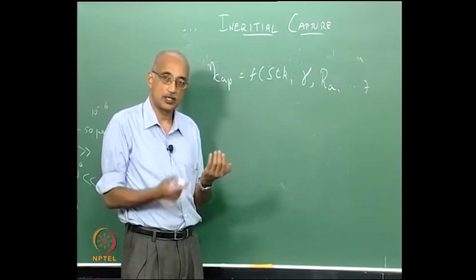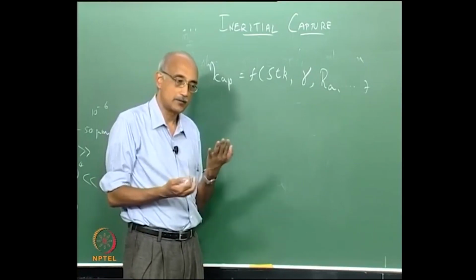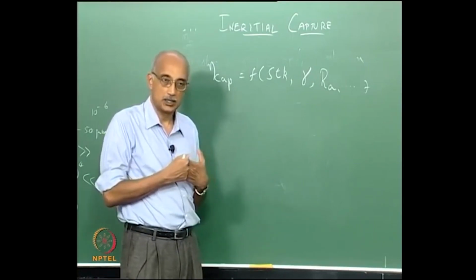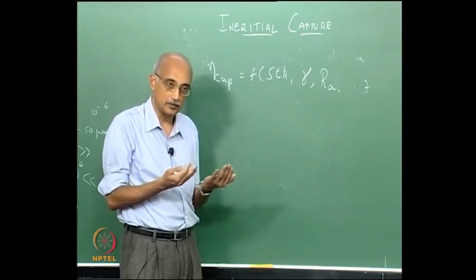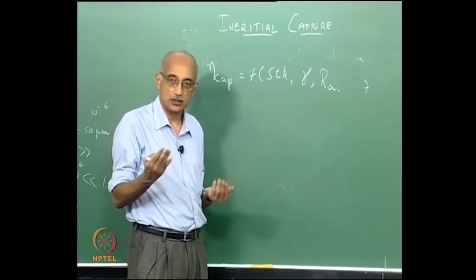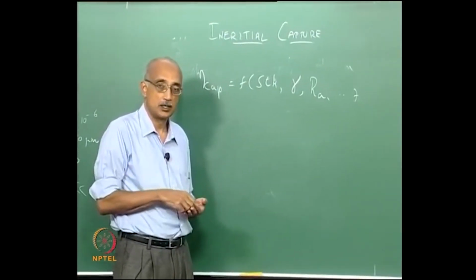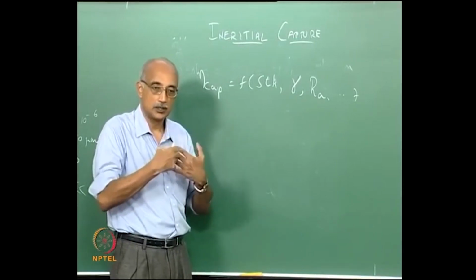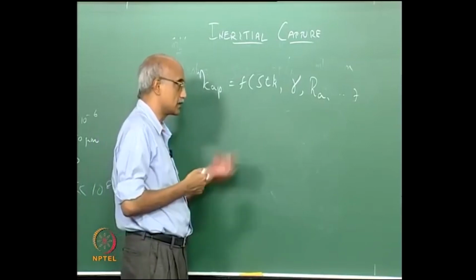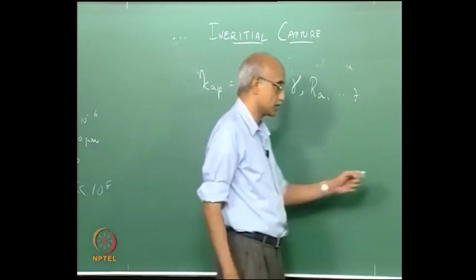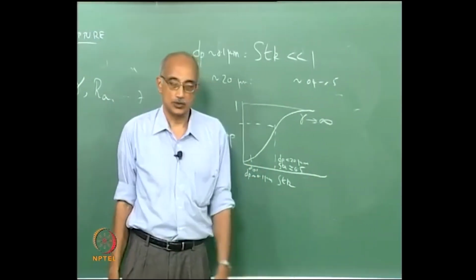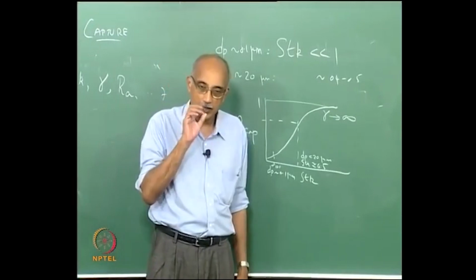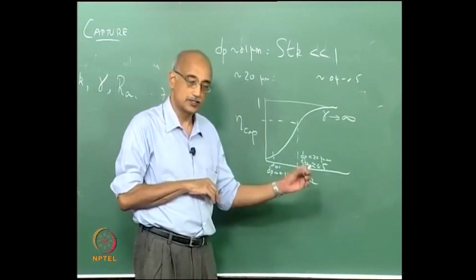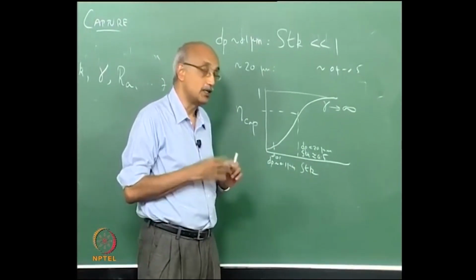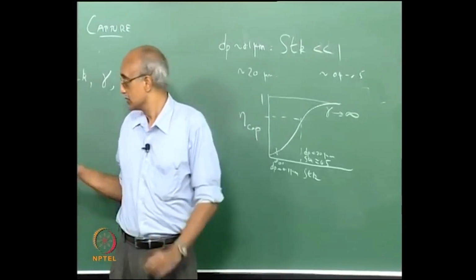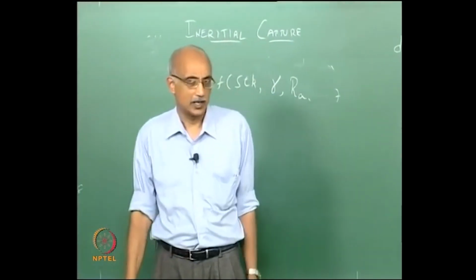Remember the discussion about deformable versus non-deformable surfaces - if two deformable surfaces come into contact, the adhesion force between them is likely greater because the effective interfacial area will be larger, and it will keep increasing with time as the two surfaces accommodate each other. So all of those factors come into play. This representation, that capture efficiency is only a function of Stokes number, is an oversimplification to highlight that particle transport plays a significant role. But a material scientist or metallurgist would argue that these aspects are just as important, if not more, and I would agree.